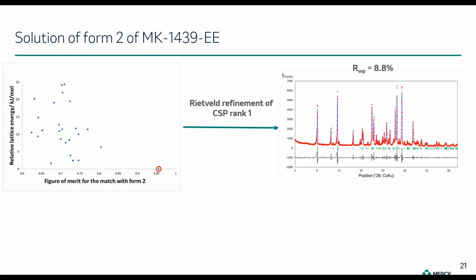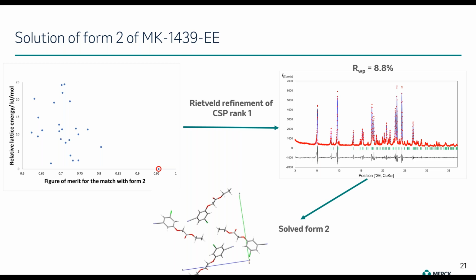So in this plot here, I show the results of this analysis. On the y-axis, I'm showing the relative lattice energy of the crystal structures generated by this targeted CSP study, and on the x-axis, I show a figure of merit for the match with form 2 of this compound. A higher value means a better match, and you can notice that there is a very obvious outlier. The lowest energy crystal structure is also the one that has a significantly better figure of merit for the match with Form 2. So we used this global minimum as a starting point for Rietveld refinement, which was successful. And in this way, we were able to fully solve Form 2 and get its full 3D coordinates.